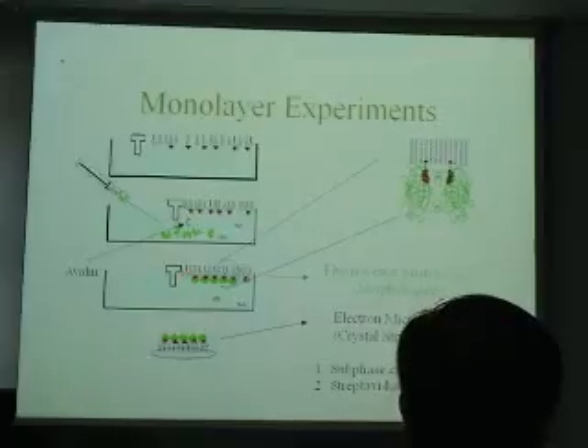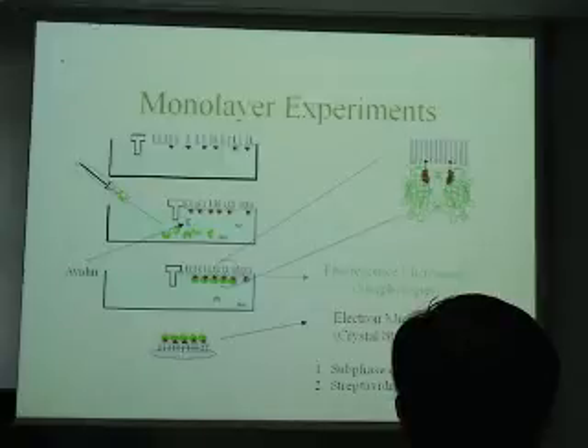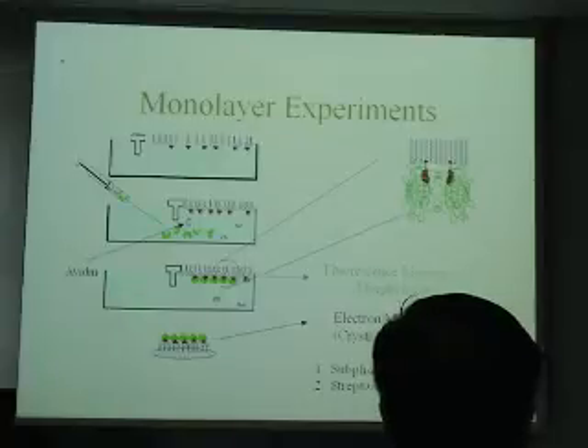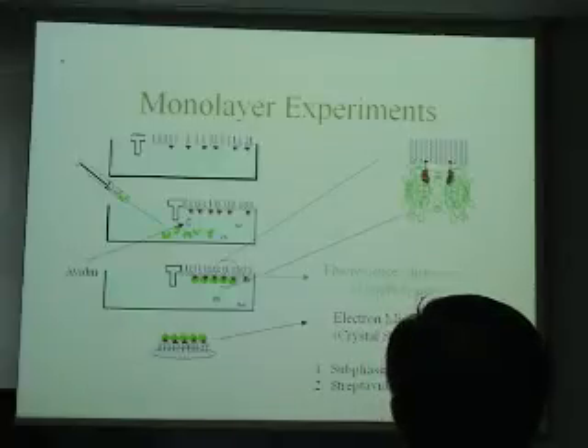So this organization serves 2 purposes. It brings the streptavidin to a higher concentration in the monolayer, and it orients it, so it reduces the number of degrees of freedom. And streptavidin was actually first crystallized in 2 dimensions when it wasn't crystalline in 3 dimensions because of this reduced degree of freedom. It orders quite readily and forms crystals quite readily.